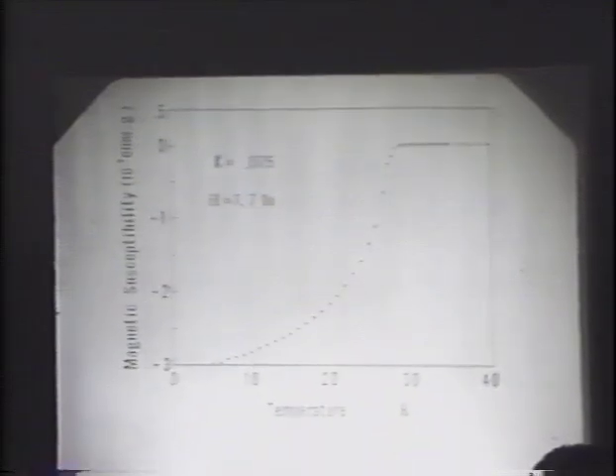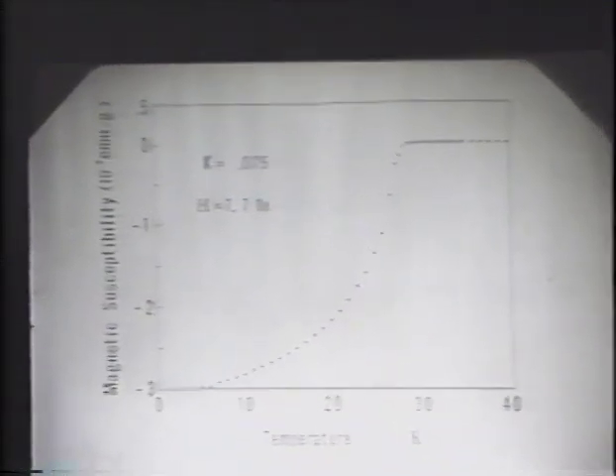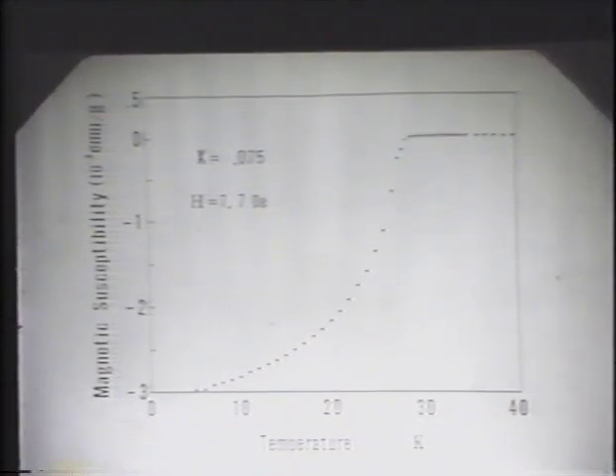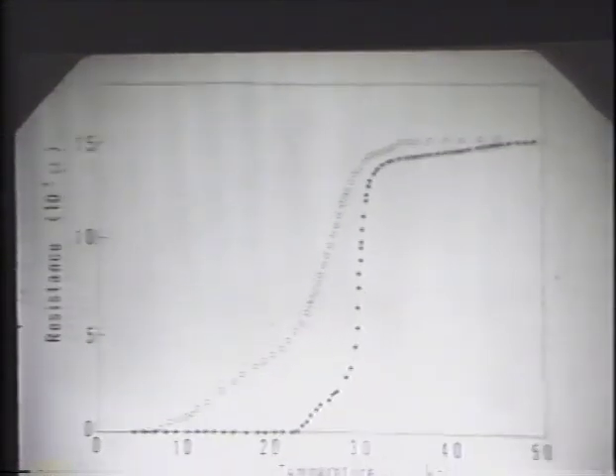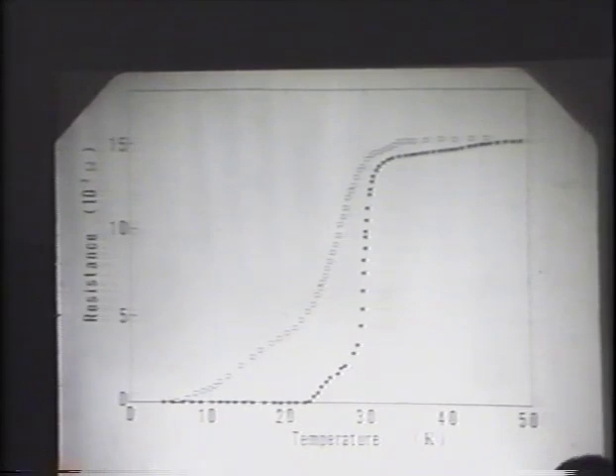From November to early December of last year, we concentrated our effort on identification of the superconducting phase in lanthanum barium copper oxide, which was first suggested as a high TC superconductor by Dr. Bednorz and Müller. We succeeded to identify the superconducting phase, and it is lanthanum barium 2 copper O4, having the K2NiF4 type crystal structure. We succeeded to make single-phase samples of this type, and the temperature dependence of diamagnetic susceptibility and resistivity indicated that this material is a bulk superconductor and the critical temperature is about 30 degrees Kelvin.